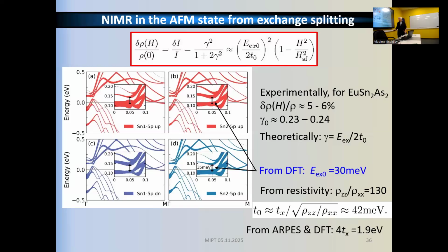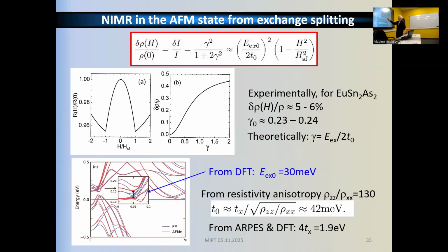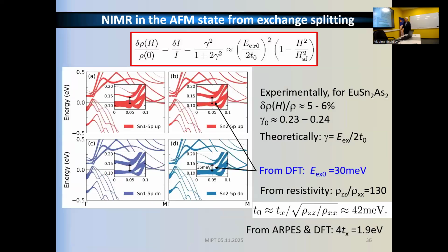And the conduction bandwidth. So from this, the bandwidth is huge, and we immediately obtained an estimate for T naught transfer integral, which is 42 meV. From these two numbers, we can get 30 by 84, so it's an order of 0.4, while experimentally we have 0.23. But resistance you measure in the plane, not perpendicular. Both. In plane or perpendicular, we scale it by the spin saturation field, and it becomes beautifully isotropic. Now we have a more or less consistent estimation of this mechanism.